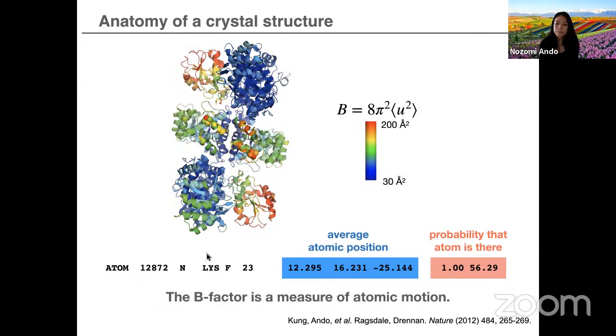It's describing the fact that even within a crystal, which is very ordered, the identical atoms in different cells and different copies of the protein are not exactly in the same place, right? So even though a crystal structure appears static, there is atomic motion still happening in the crystal, which we expect of any real crystal. And here I've colored the structure in terms of the B factor. And the B factor is related to the mean squared displacement. So U is the displacement from the center. If you imagine these blue numbers, that represents the ideal position of the atom, but it's not always there. It's fluctuating about that point with displacement U. And that's what the B factor is telling us here.